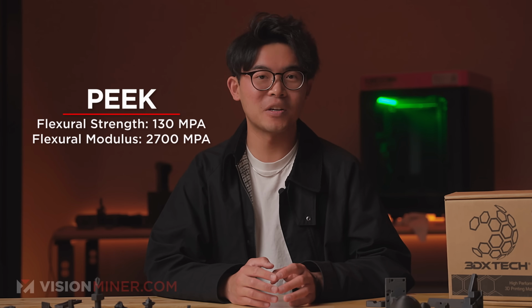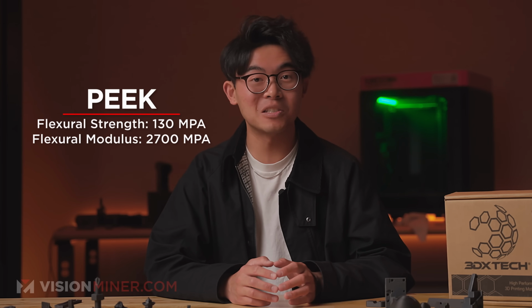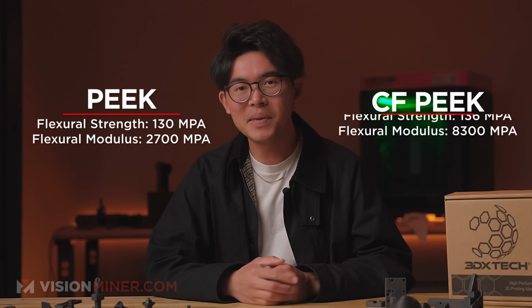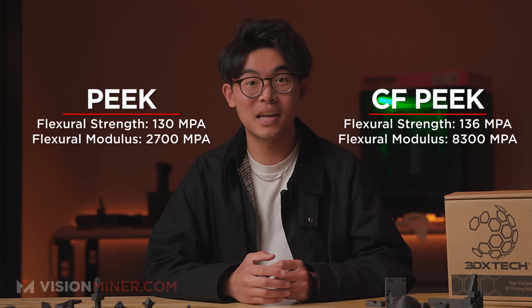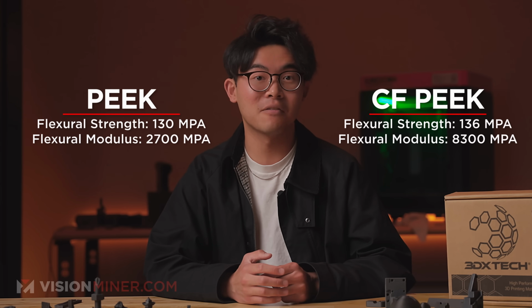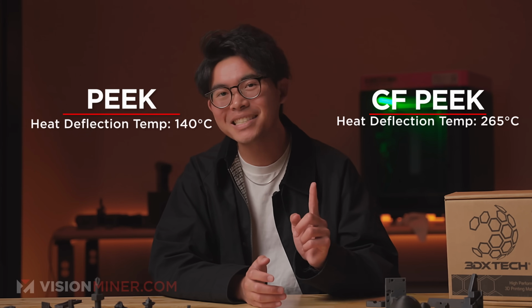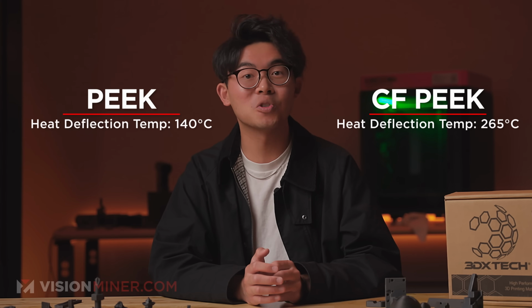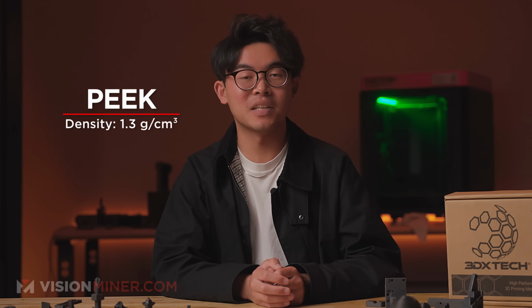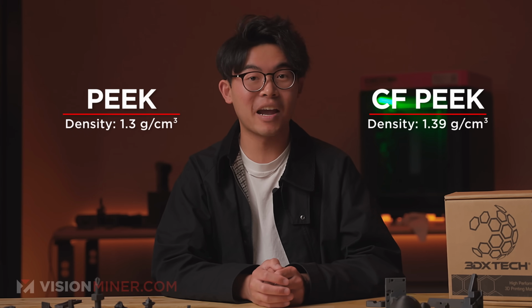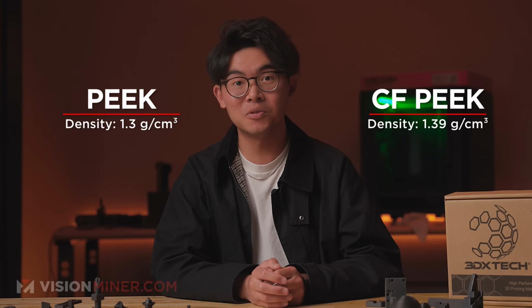Regular PEEK has a flexural strength of 130 megapascals and a flexural modulus of 2,700 megapascals. CFP offers 136 in flexural strength and 8,300 in flexural modulus, far stiffer and more resistant to bending. Regular PEEK has a heat deflection temperature of 140 degrees Celsius, while CFP can handle up to 265. This makes CFP much more suitable for high temperature environments. Regular PEEK has a density of 1.3 grams per cubic centimeter, while CFP is slightly denser at 1.39 grams per cubic centimeter due to the additional carbon fiber. This means a little bit of added weight, but the performance gains outweigh this minor increase.